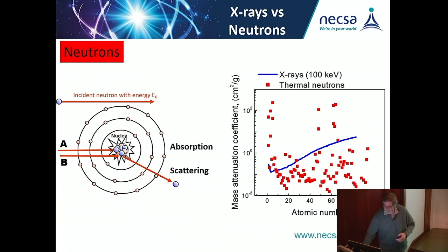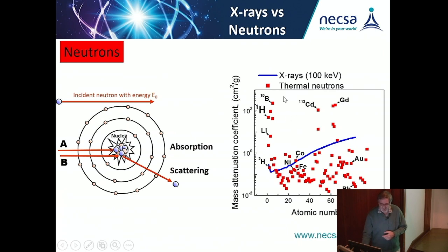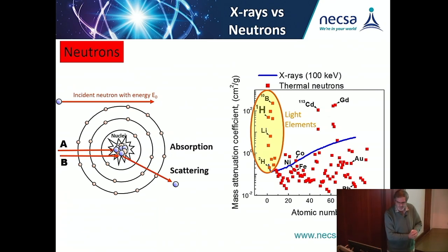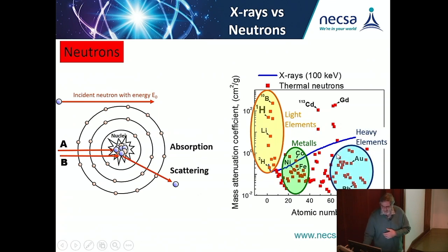So what we can see here is that the light elements, boron, hydrogen and lithium, are attenuated or scattered by neutrons in a higher manner than by X-rays. So you can detect the signal of hydrogen, boron and lithium much better using neutrons than X-rays. What about the metals and the heavy metal elements? Here we see that penetration using neutrons is much better through those elements than using X-rays. If you look at lead, even X-rays can't penetrate through lead, but with neutrons, lead is very low on the mass attenuation coefficient scale, so you can penetrate lead very easily. So you can't stop neutrons using lead.